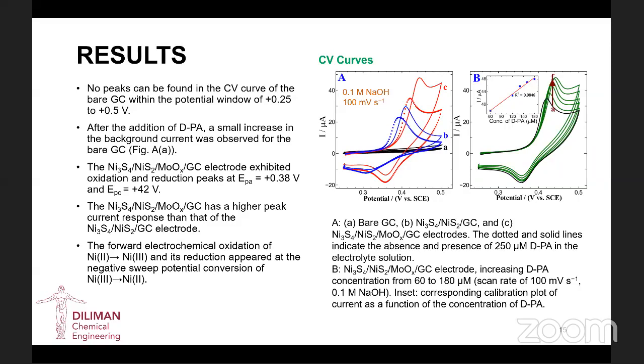CV, or cyclic voltammetry studies, and if you see image A, curve A, there are no peaks in the CV curve of the bare GC given the potential window here. And then after the addition of penicillamine, a small increase in the background curve was observed for the bare GC. The dotted lines here represent the absence of DPA, whereas the solid lines represent the presence of 250 micromolar DPA in the electrolyte solution.